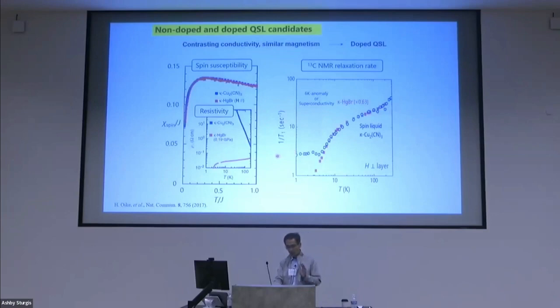Firstly, I'd like to show the magnetism and conductivity of the two materials. If we take a look at the inset, which shows the resistivity of the two materials, the non-doped quantum spin liquid candidate shows insulating behavior because this is an insulator, of course. But the 11% hole-doped system shows a metal, a little bit here. So the behavior is quite different between the two systems.